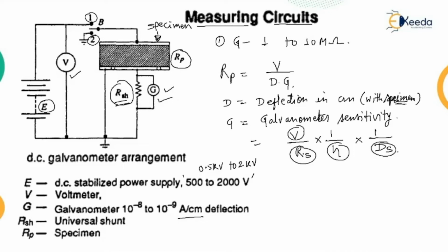Rs is the standard resistance used for calibration, and V is the supply voltage. It may be noted that the deflection with the specimen in the circuit will change with time. The initial high deflections indicate the high charging current required by the dielectric specimen. So dielectric specimen, insulating specimen, which is placed here. For the purpose of calculations, the steady current obtained after a considerable long charging time should only be taken.